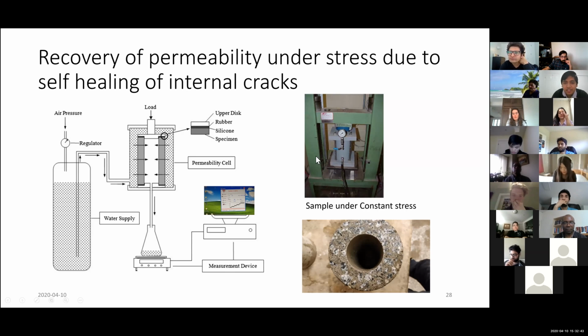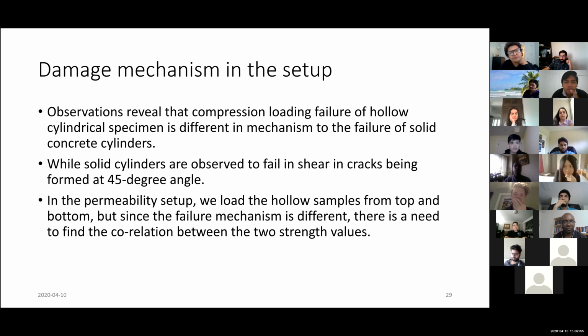So we can leave one of those samples under stress, or we can have this cell outside without stress as well. So there are two ways that I can approach this test. What I observed while I was doing this test is that compression loading failure in the hollow cylinder is different to the compression failure in any solid cylinder.